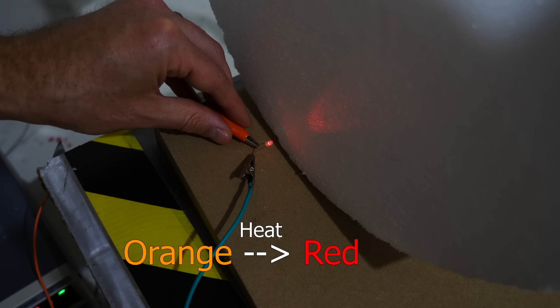So you can see as I crank up the voltage it goes from yellowish-orange to more red. That's because as the temperature went up, the band gap decreased, and so the photons coming off of it are less energetic actually, even though the temperature is higher.